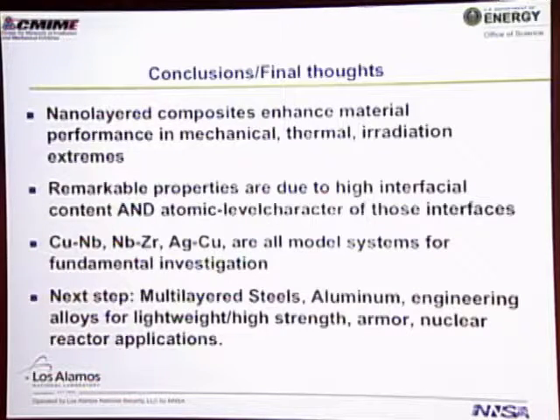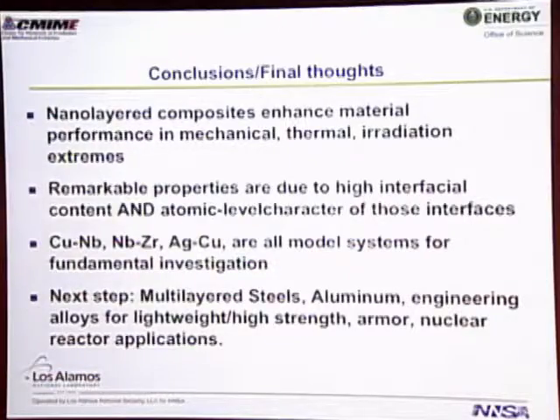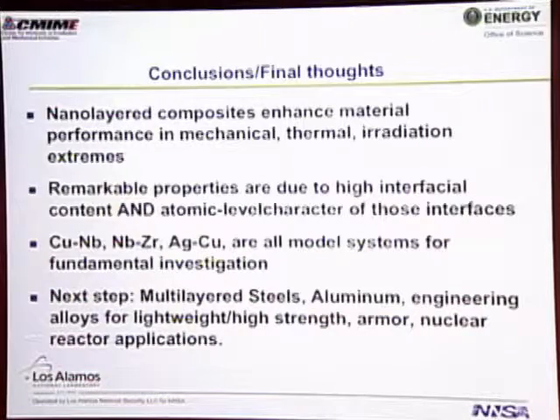So today I talked a lot about copper niobium, but we've also looked at materials such as niobium zirconium, silver copper. They're all model systems for these investigations. They're materials that we know a lot about. The eventual goal here is, of course, you're not going to make your car or your airplane out of these types of materials. The next step here is to make multi-layered steels. Take these interfaces that we have discovered here. We know that they're good for radiation damage. We know they're good for high strength. Take those interfaces, put them into a steel product. Put them into an aluminum product or another engineering alloy. Then you can start making these lightweight, high-strength materials where you can use them as an armor or put them into a nuclear reactor.